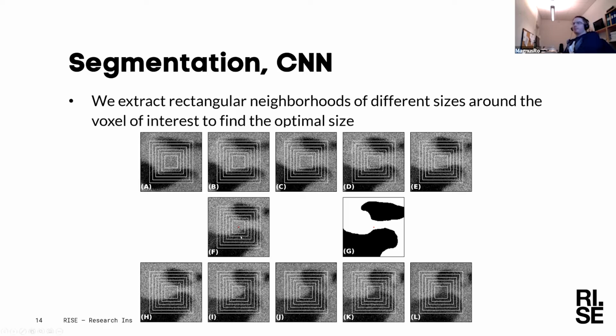So basically, roughly speaking, the solid parts are going to be somewhat brighter, and the pores are going to be somewhat darker. But it's not that easy, considering that you would have a shine-through effect, as they call it, that you see a little bit of the material that you have further into the structure. But very roughly speaking, the brighter parts are solid, the darker parts are pores.